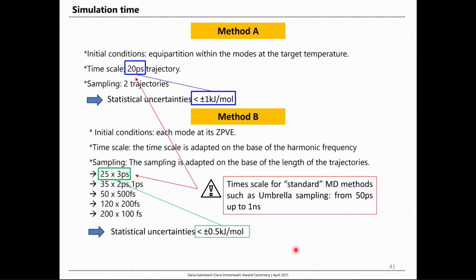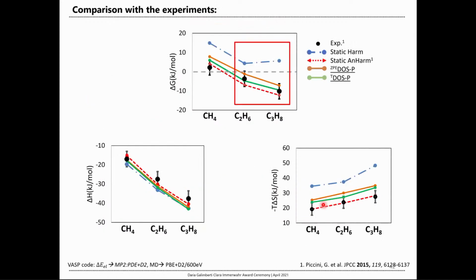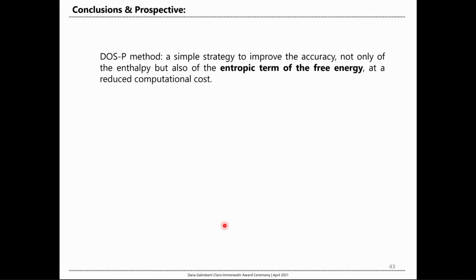And with these 3 picosecond trajectories, you can see from this brown line here and here that we can still have a good prediction of the adsorption free energies for these 3 cases. So with this, I would like to conclude. I hope I convinced you that we have a simple strategy to improve the accuracy, not only of the enthalpic term but also of the entropic term of free energies, with a reduced computational cost, because 20 picosecond trajectories are something that we can now do in a couple of days, or 1 week if your system is big.